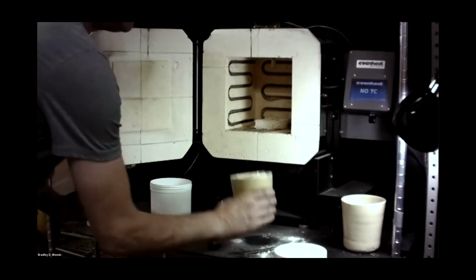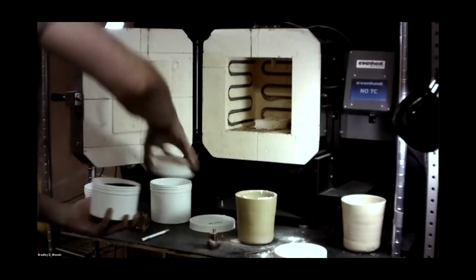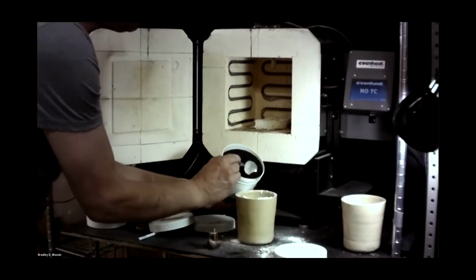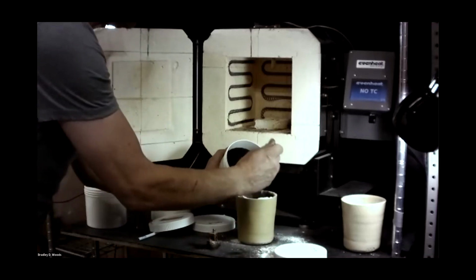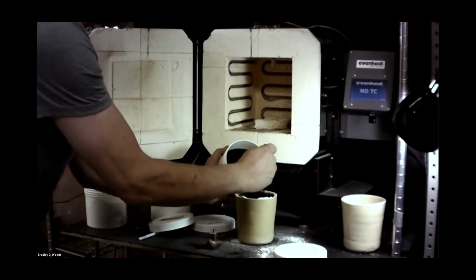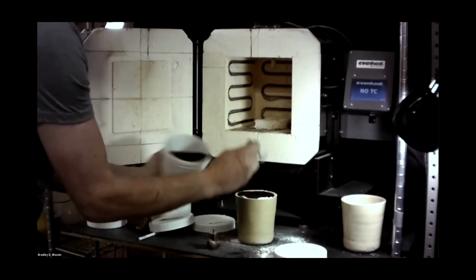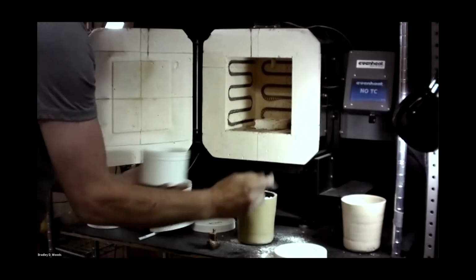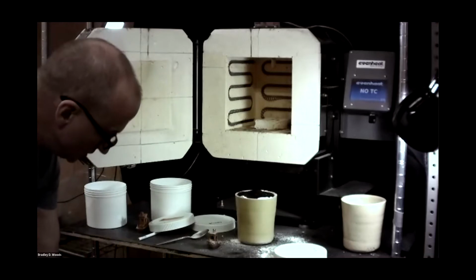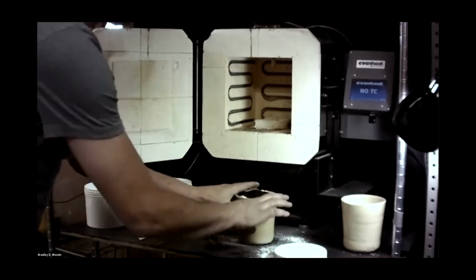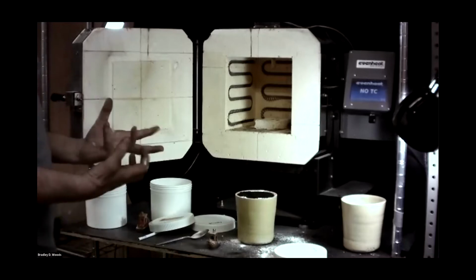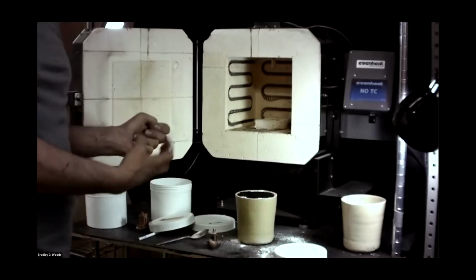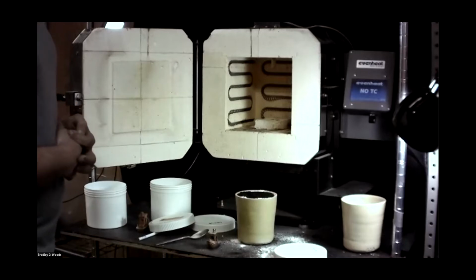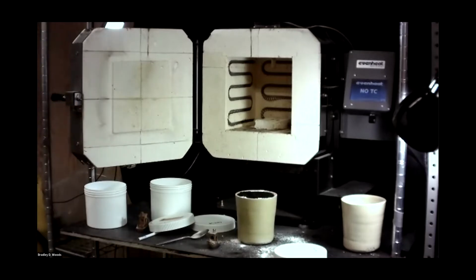So on top of the talc, we'll get that settled in there and top it off with sintering carbon. Now, you really can't use too much sintering carbon. Whatever is left over at the end of the process, you can filter out and reuse again. Right. And the best way to conserve this stuff is it will all be there except what has been exposed to oxygen and got consumed. So to maximize your efficiency on the carbon is to use...